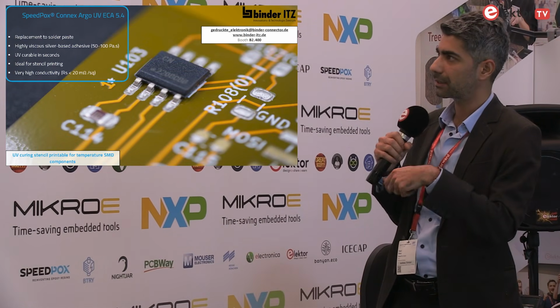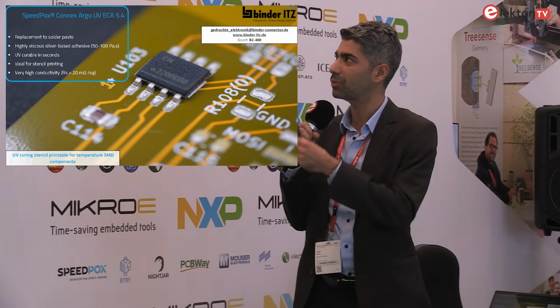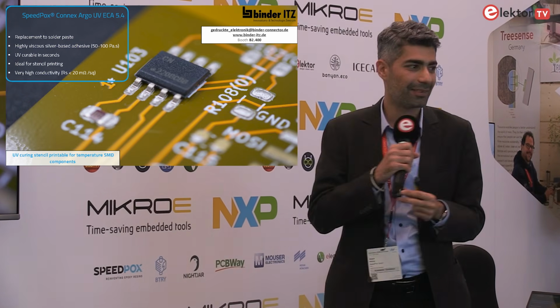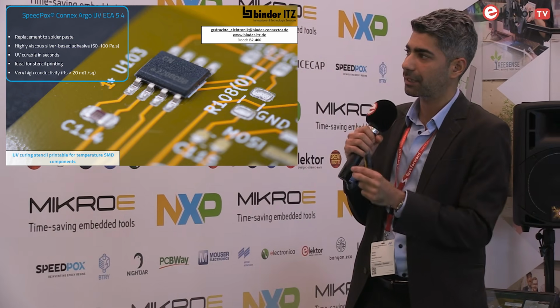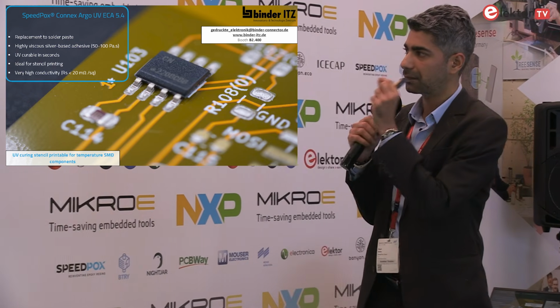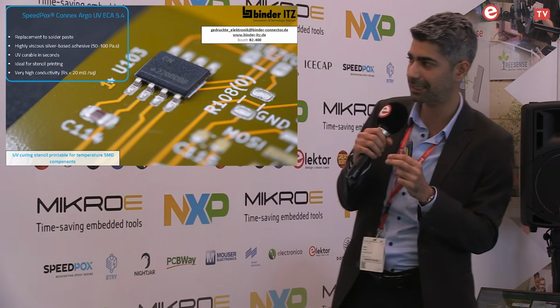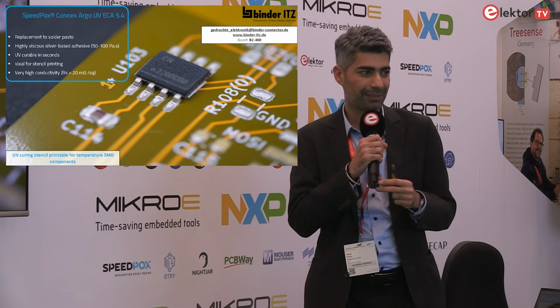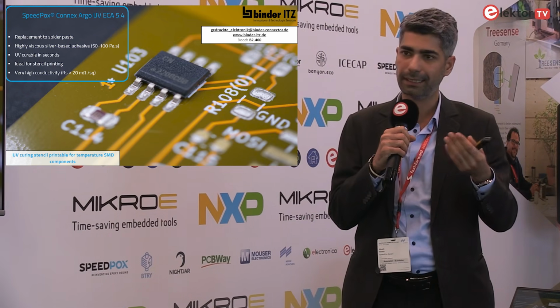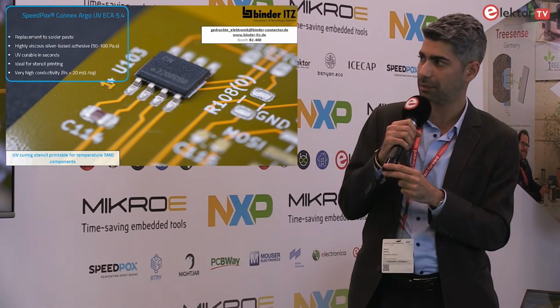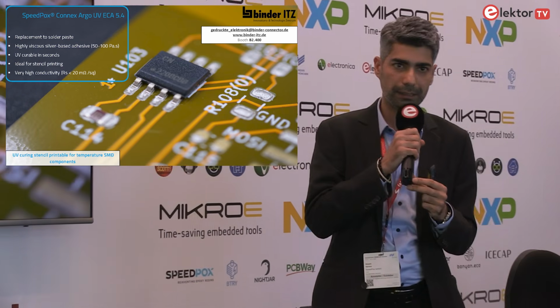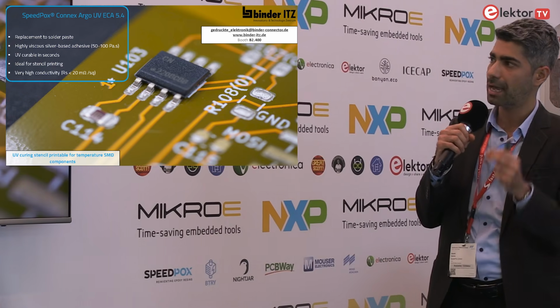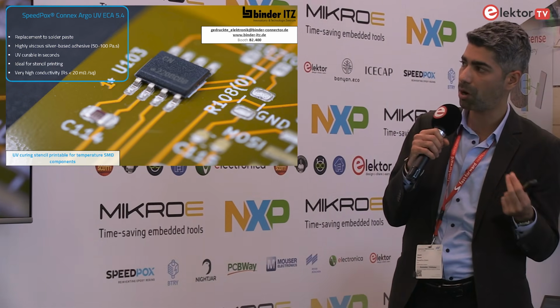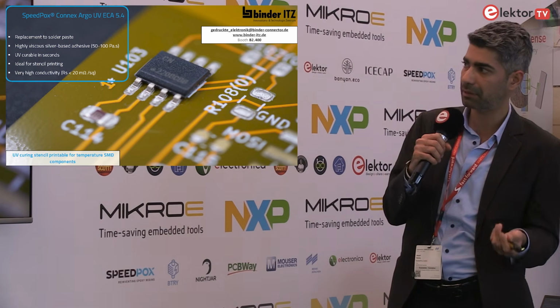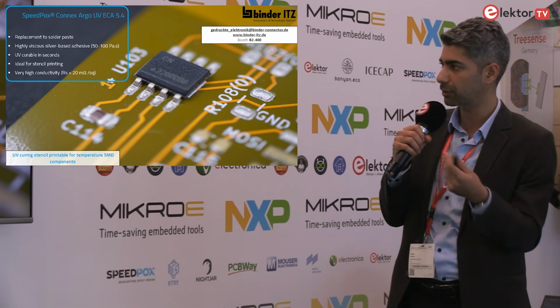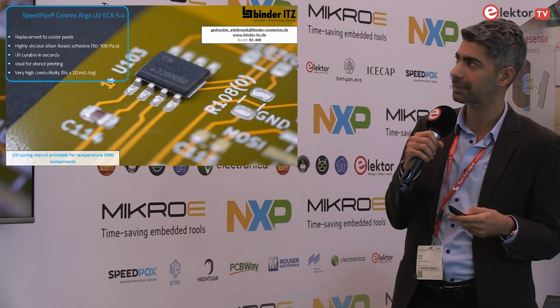And moving on to another application with Binder, who also have a booth here in B2 hall, where you can see that instead of jetting, we can also use silver adhesives that can be stencil printable. The current issue was that the current adhesives cannot be cured at more than 80 degrees, and there were some issues for short circuiting. By developing a silver adhesive, which is highly viscous in nature and UV curable, we are able to bond such kind of IC chips on different substrates for use in printed electronics and sensing applications.